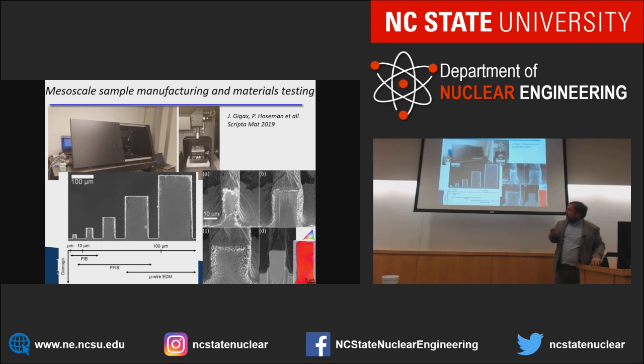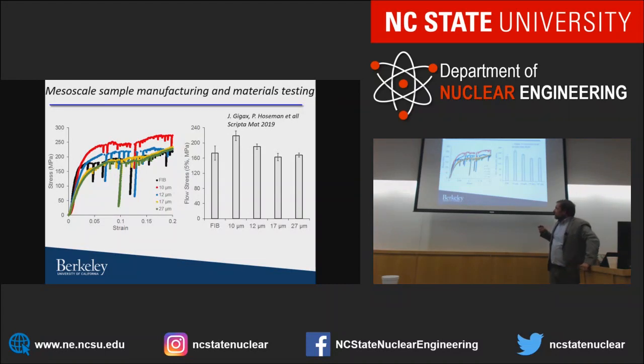And so Jonathan did ion beam irradiation and made these in copper and cut them to different sizes. If we just make them by FIB, that's the reference, that's the black line, and all those other lines are laser manufactured ones. And the question is, how much material do we have to remove to get to the same mechanical property? So it turns out, if you do just conventional ion beam machining, this is what you get as a flow stress. If you do 10 micron pillars with the laser, and you don't remove material, and you cut away to the same dimension as the FIB, you get this much increase.